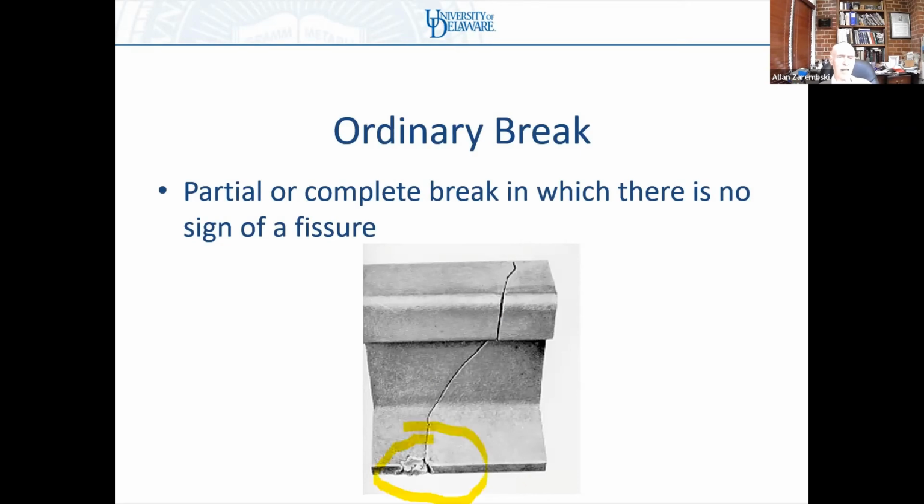So if you look down here, you see this dent over here. Very often associated with a guy with a sledgehammer or a spike maul, or even a tamper. I've even seen tamper damage, even though it's less common with a tamper, causing a stress concentration on the base of the rail, which multiplies the stress, and then the defect will propagate vertically through the rail without any sign of a fatigue defect per se. It will just be a crack propagation through the rail.